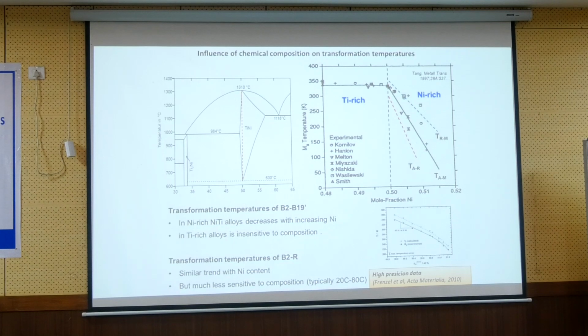But yeah, there is something interesting about the B19' phase, that the physicists who model the structure of materials never find it as an equilibrium structure. You know? And you are completely right that in some special cases they found it. But one has to be careful with taking this information from the literature, again because it's at 0K, temperature effect, composition effect, and so on. Okay, good.